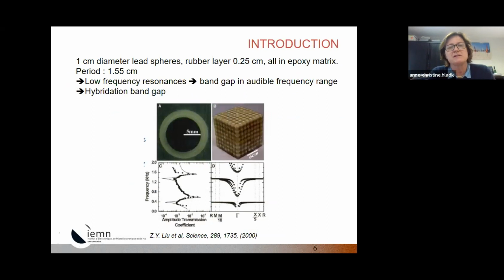For the previous case, the problem is that if you want a good efficiency, the thickness has to be large because you have to take into account several periods. So it can be very heavy, and it is rather high frequency. If you want to have a band gap at lower frequency, you can use resonances. In that case, we call that a hybridation band gap.